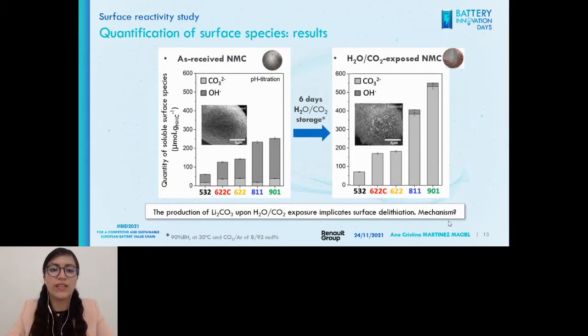You can see that the amount of carbonate is almost constant. However, the amount of hydroxides—that later we discovered is not hydroxide, it's lithium oxide—is increasing.